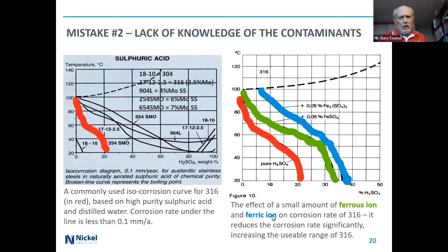But if we have a small amount of ferrous or ferric ion or any other oxidizing ion there, it extends the use of 316L. So even with a little bit, 0.05% ferrous ion, you can use 316L at close to 35% acid. This is at 20 degrees C, you'll be fine, as long as you maintain that amount of oxidizing ion, but you have to maintain a minimum of that level there.